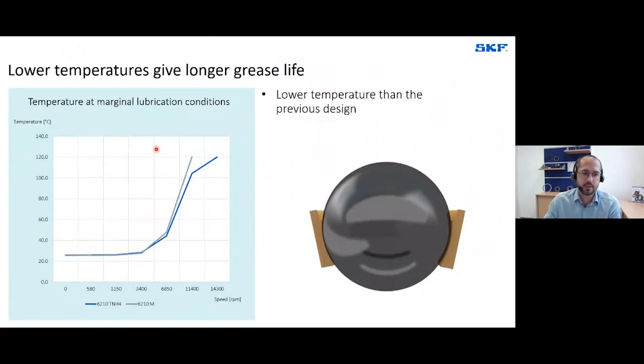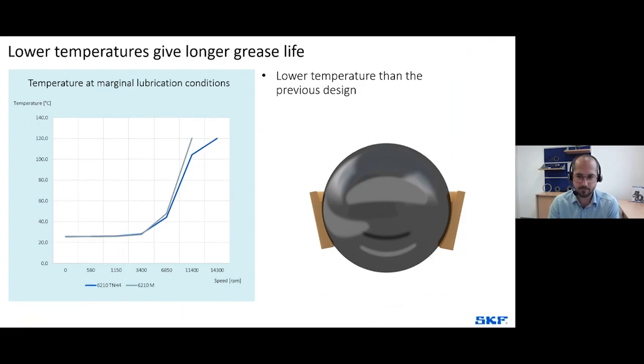And the third effect, which is again very important for high-speed applications, is that the heat development at those high speeds is significantly lower than in an equivalent hybrid bearing with a brass cage. And actually, it even allows us to go higher in speed because temperature development is slower and lower in general. So as we're all confronted with the challenge for increased power densities sooner or later, we all need to think about better or upgraded bearing solutions, and hybrid bearings is definitely a solution suitable for increased power densities.